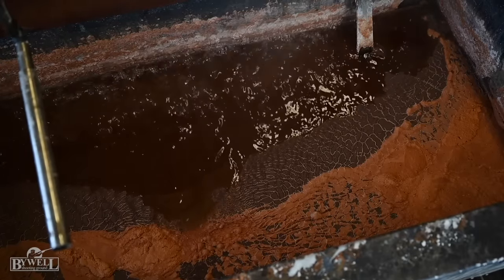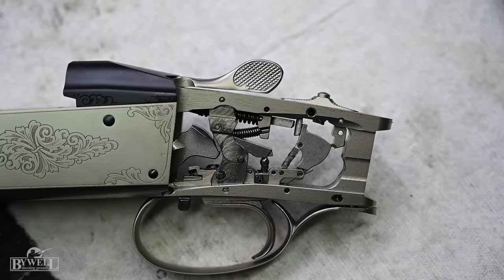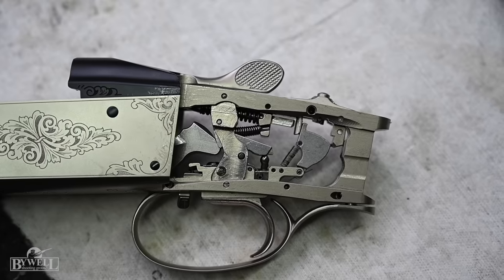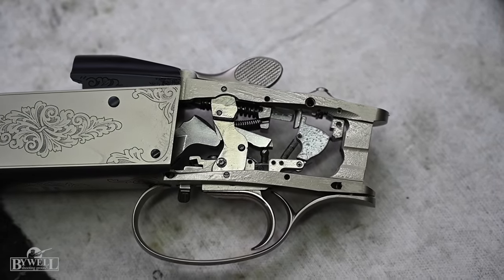So this is a problem because we have fitting areas on all the cross holes, and we would need to mill it back off again. Exactly, we should actually. What we of course don't do, because you cannot put the finished receiver back onto the CNC machine, that's impossible. That's why we do a combination process. That means for the first two thousandths of a millimeter we do electro nickel plating, so we have the strength of the nickel holding onto the material quite well. And for the rest of the thickness for the corrosion protection, we do chemical nickel plating because the chemical builds up parallel to the receiver. So we have the advantage of both versions, and that's why we do a combination process.